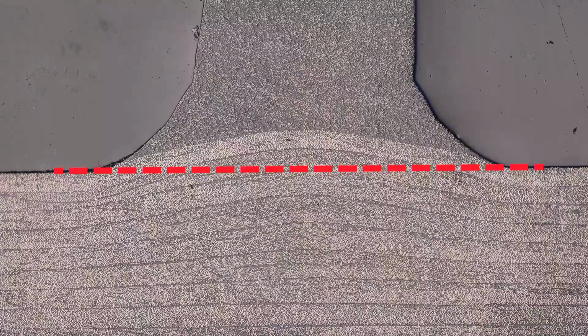And what's happening is that during the process, we heat up a laminate above its melting temperature, and then we place it in the injection molding machine, and the injection mold closes, and at that point the laminate reconsolidates. But at the locations where you have those ribs, you don't have any pressure at the moment. So what happens is that the fibers are pushed into the cavity, and